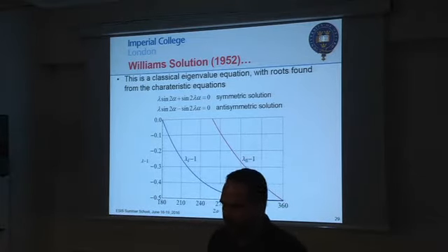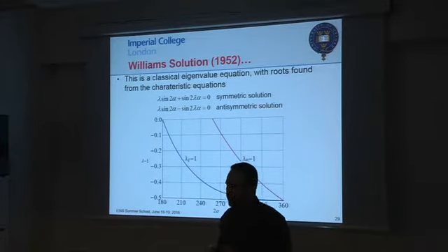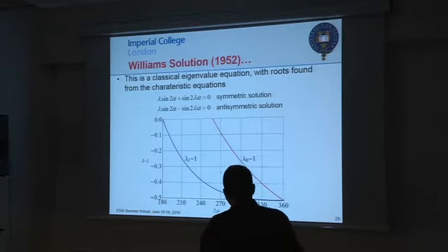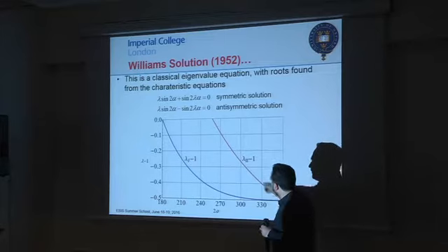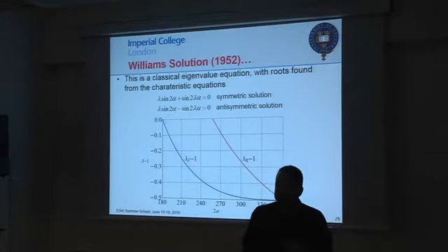Your stress field becomes what we call bounded. So your solution goes from a certain form to a completely different form. And what it means is that the solution, definitely from that point onwards, is always dominated by mode 1.